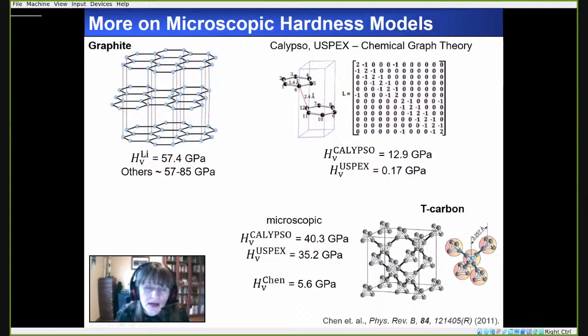Micro-hardness models have been shown to fail for systems where you do have non-bonded interactions, such as in graphite. They predict unreasonably high hardnesses. But the bonding models within Calypso and Uspex use chemical graph theory to correct for this. However, there are still cases where the micro-hardness models fail.